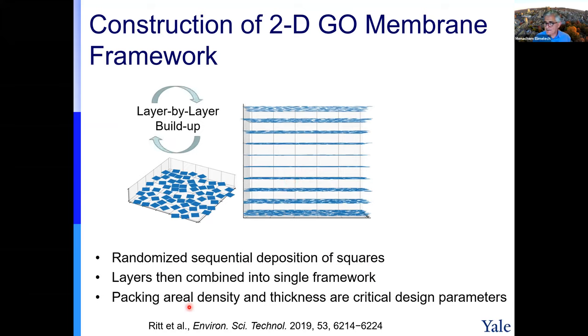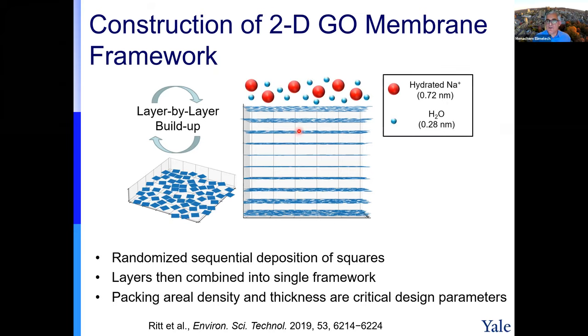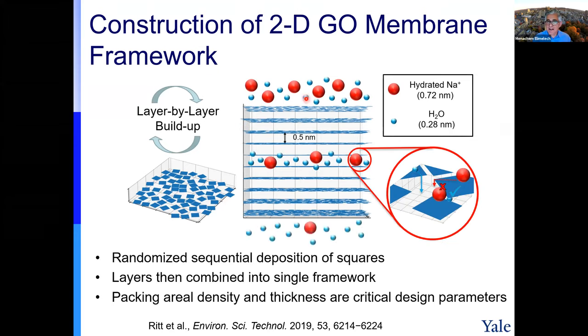Two important parameters in this membrane. First is the packing areal density. Areal density describes what fraction of the surface will be covered by the nanosheets that you see here. And as you see, just from this process, if you have anything the same size, you will never be able to get more than 54% coverage without overlap. And we avoid overlap because once you overlap, you will get all this tilting and it will affect all the performance of the membrane. We simulated this process, created membranes, and then challenged them with sodium, the hydrated ion, and water molecules. And then we were able to do a kind of experiment and get the salt rejection and water permeability.